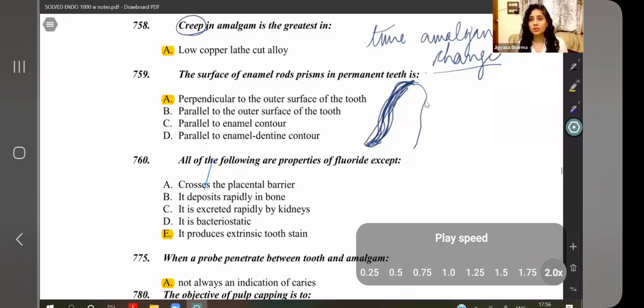Why does the shape of the amalgam change? It changes because more corrosive products get formed, and because of that corrosion, the shape and size of the amalgam changes. So if creep is the response of corrosion, what leads to corrosion? More gamma 2 phase, that's your tin mercury phase. Those are the weaker components leading to corrosion. So if your gamma 2 is linked with corrosion, what has more gamma 2 phase? Low copper or high copper? So it's your low copper lathe cut.